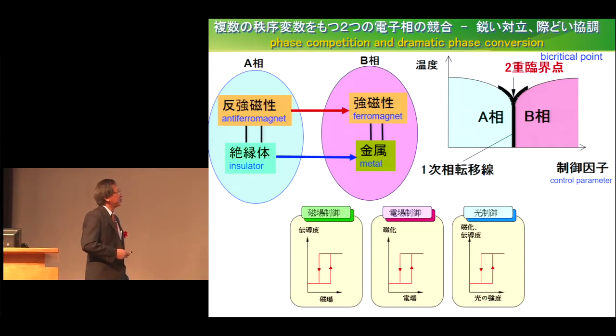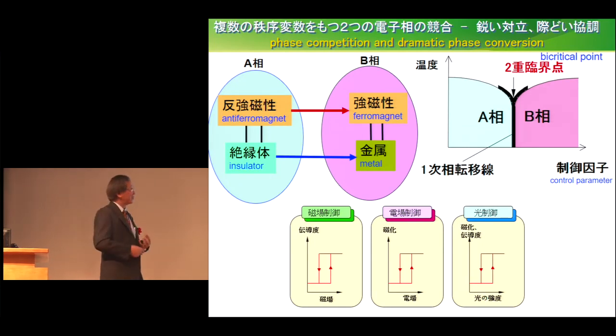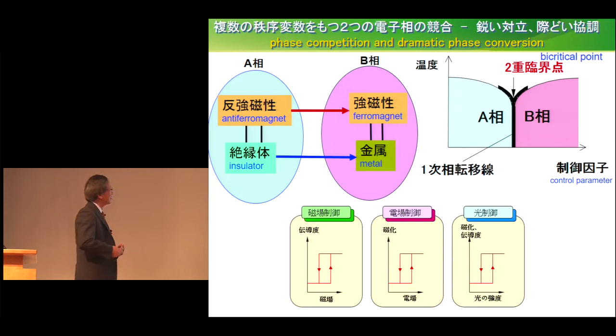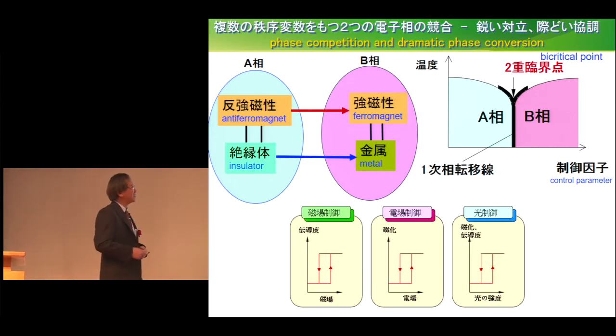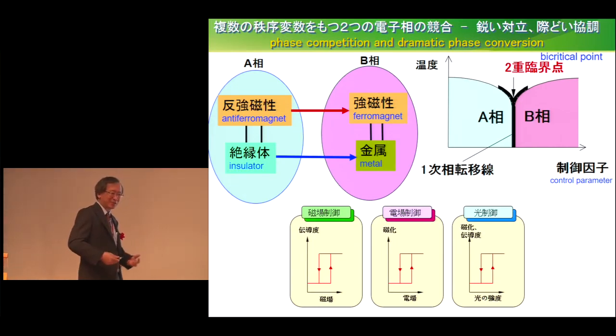For example, the anti-ferromagnet and the insulator, just like the pair of ferromagnet and the metal. And if we can combine them with the spin, charge and orbital, if there is a competition at a certain temperature, by changing the composition or the magnetic field, we can change these phases, A and B. This is like insulator against metal, anti-ferromagnetism and ferromagnetism, and there is an instantaneous change between the two phases. But the competition continues to the last moment, then there is a compromise.